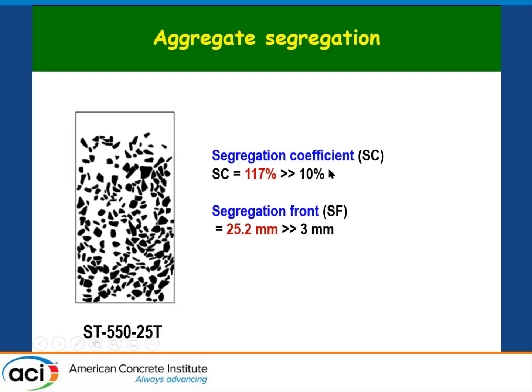But vibration or overstriking might also lead to segregation. So we cut our specimens open after every cycle of striking or at the end of vibration. And we looked at 2 indices. The first one is segregation. So we evaluated segregation coefficient. I'll show an example of that.